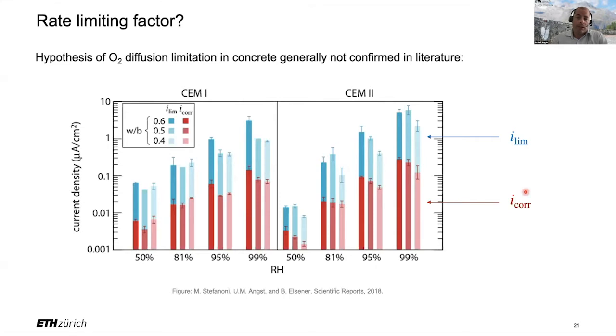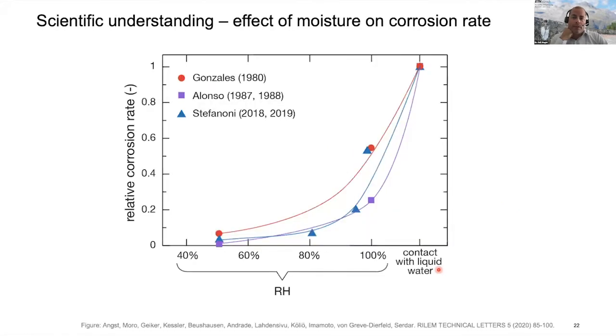And these are results that were done in 2 different cement types, 3 different water binder ratios, and a broad range of different relative humidities. So it seems that the oxygen diffusion limitation is not really the controlling factor, which is the rate limiting step for corrosion of steel in carbonated concrete. So what else then can be used to describe and quantify the corrosion rate in concrete as a function of the relative humidity or moisture state in general?